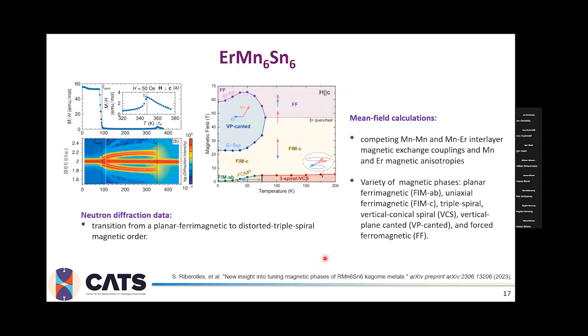As the final project, and actually the most complex, which we measured in the high field, is erbium manganese 6 tin 6, and with this we got some neutron diffraction data, which I believe Ben will be talking about later. The interesting part here is that we discovered a transition from a planar ferrimagnetic to a distorted triple spiral magnetic order at around 91 Kelvin.